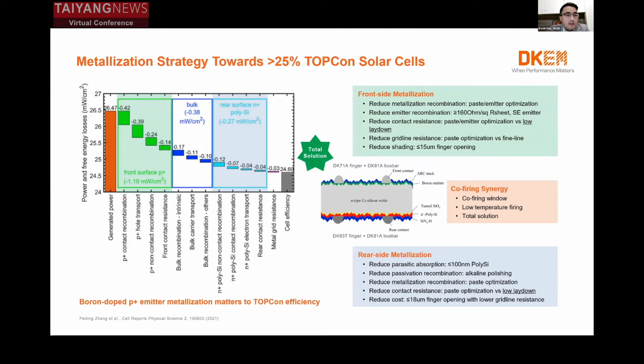As the previous talk shared, right now for TOPCon solar cells, the mass production efficiency is mainly between 24.5 and 25%. In this situation, what can we do to help customers achieve more than 25% TOPCon solar cell efficiency? Here we studied some literature, together with our metallization practice. On the left is a breakdown of the efficiency loss. You can see that the major loss still happens at the front side, then the bulk, and the second place is the rear side. That means the major opportunities are still on the front side.